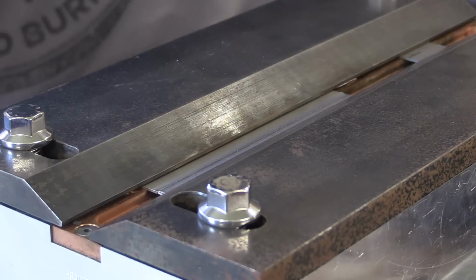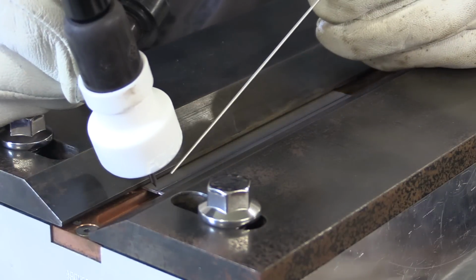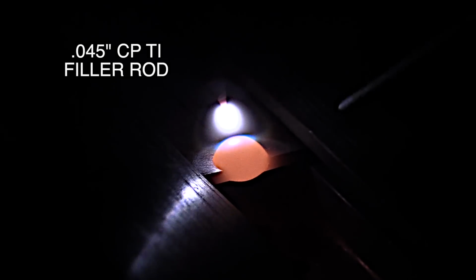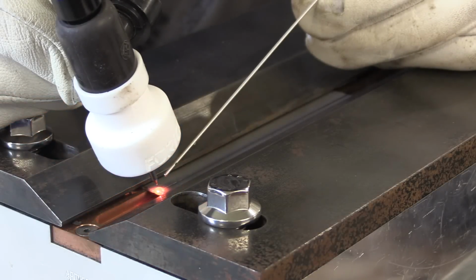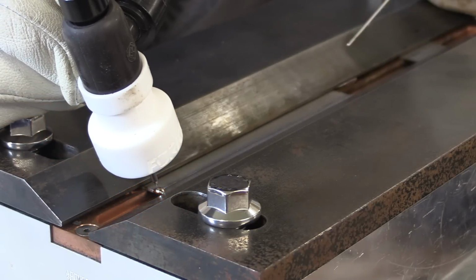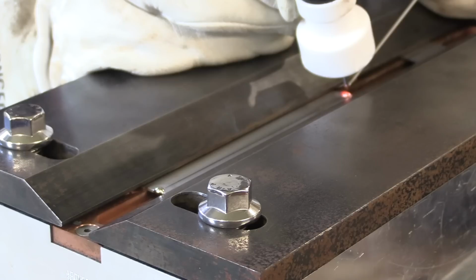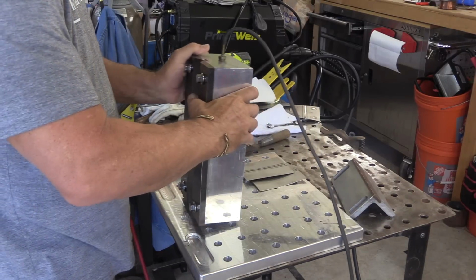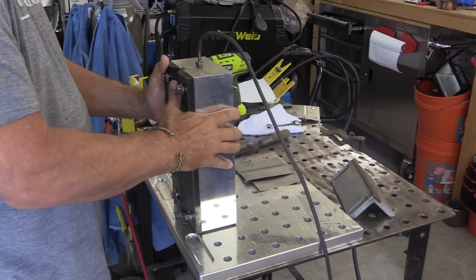Once it's in the fixture and tightened up, I'm going to get a couple of tacks, one on each end, and I'm going to put just a little bit of extra filler on each end, just a little extra dab. Gives me a little leeway when welding from and welding to keep me from melting the ends away. The D17.1 spec gives some allowance for melting the ends away, but you're not going to impress anybody by doing so. Once the tack welds are done, I'm going to stand the fixture up into the 3G vertical position and